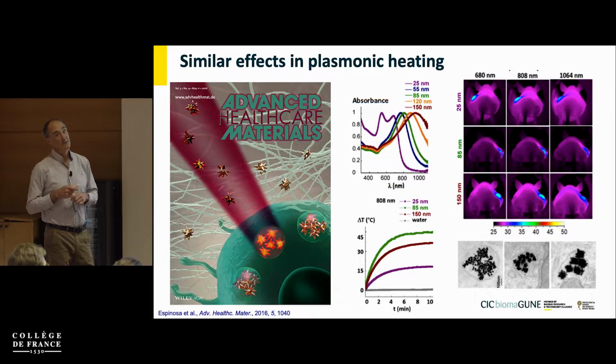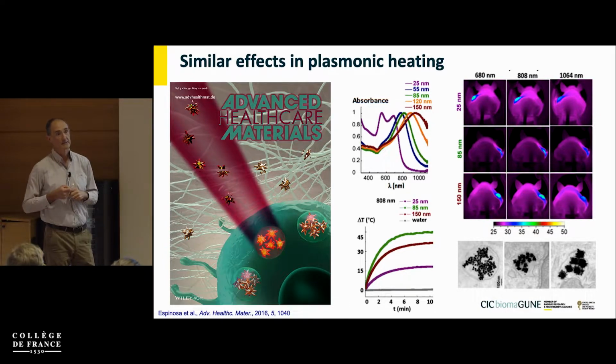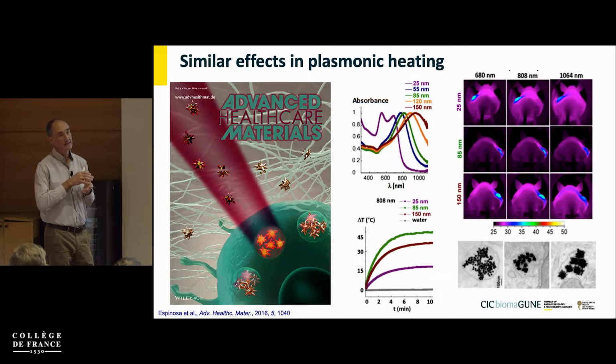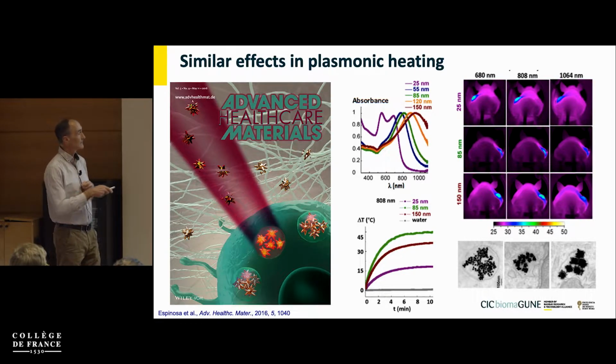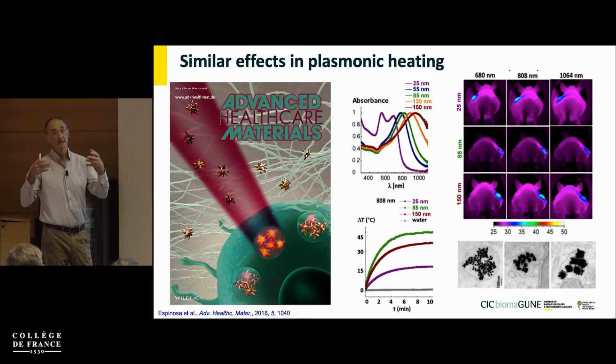And then there were some surprising results that, depending on the time at which you measure, for example, within the animal, the best response would come either from the intermediate or from the larger particles. But this was actually quite counterintuitive because we were observing that at later times, some of the stars were not so efficient, and this was related to their accumulation within the endosomes. So they start to have this destructive interference as well.